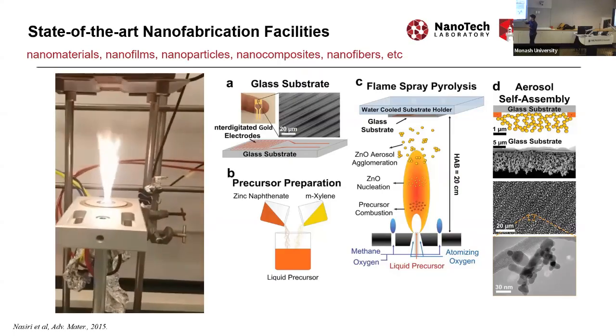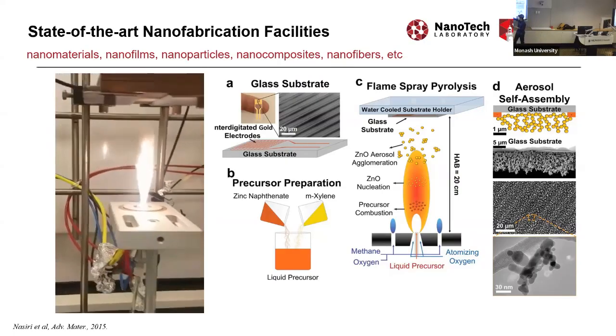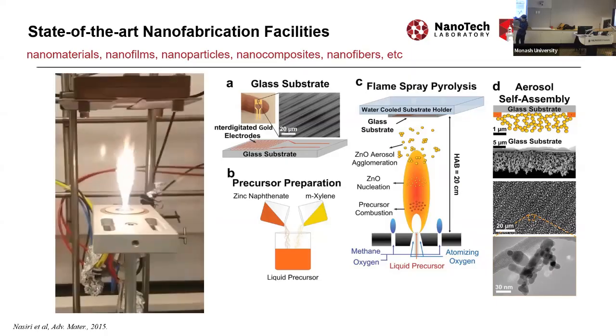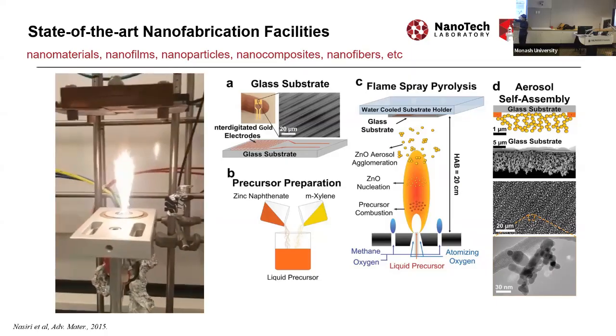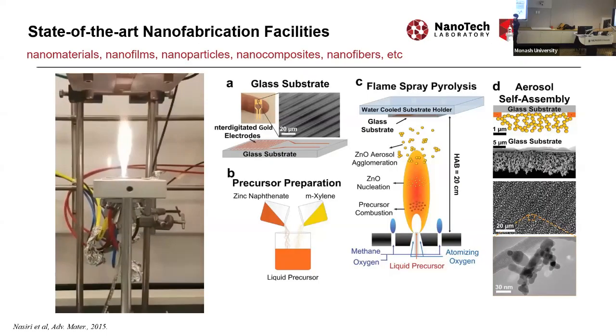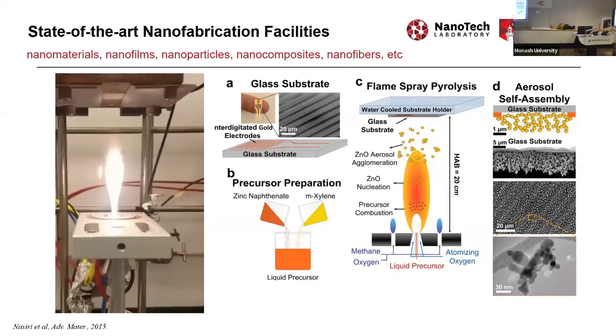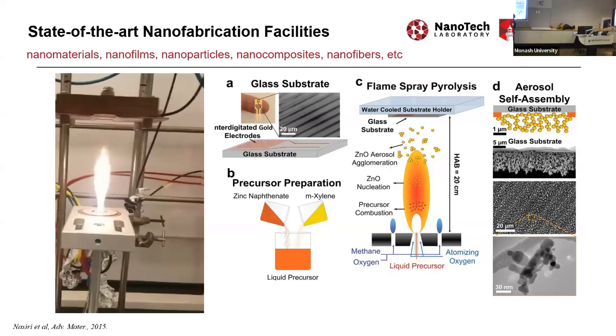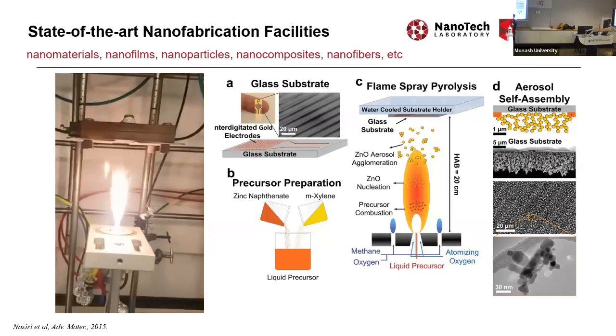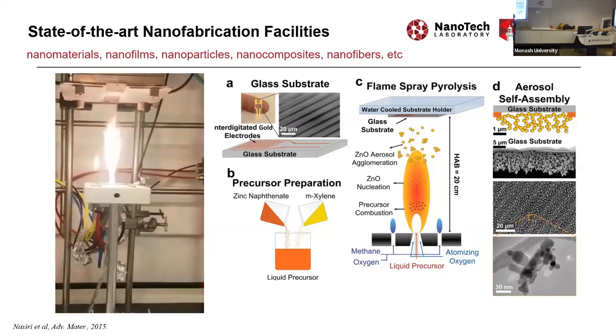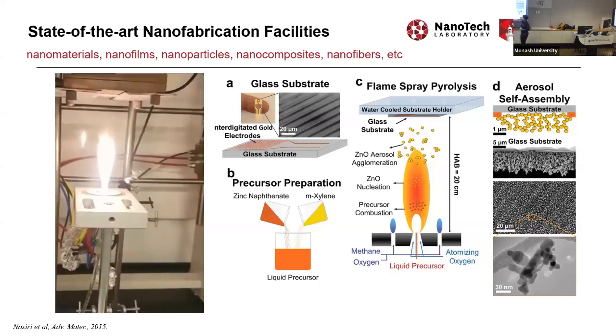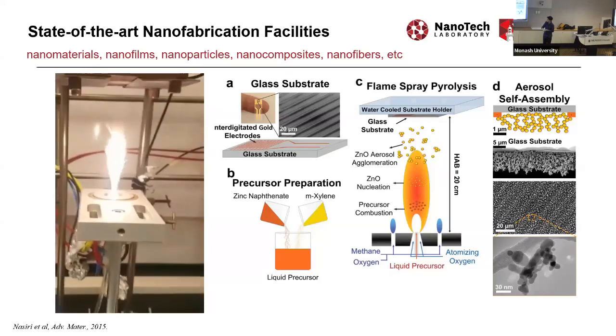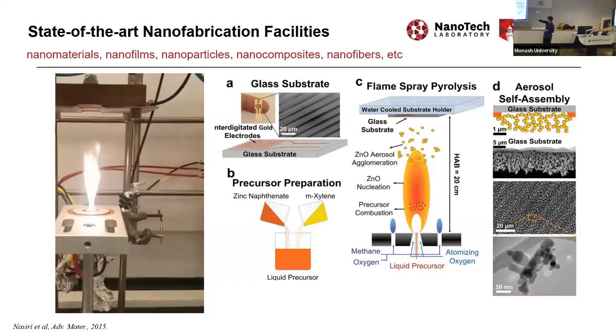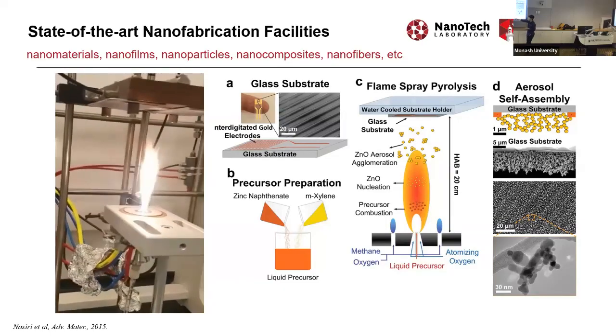And it's kind of pretty simple. This is how it works. This is an example for zinc oxide, but you can think about any type of metal oxide. If I want to make zinc oxide, I need a precursor which has a zinc source, and then I need a solvent. Both of them should be flammable, and the solvent is just to carefully define a concentration of the zinc atoms in the liquid precursor.